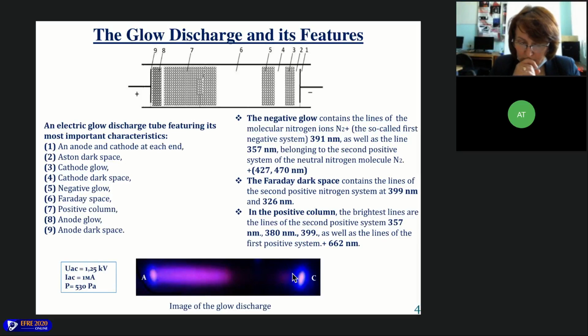There are 2 most important types of collision: excitation and ionization of gas atoms. The excitation collisions and subsequent de-excitation to lower levels by radiative decay are responsible for the characteristic glow in glow discharge. For example, the negative glow contains the lines at 391 nanometers, 357 nanometers, 427 and 470 nanometers. The Faraday dark space contains bright lines at 399 nanometers, 326 nanometers, and the positive column contains bright lines at 357, 380 nanometers, 399, and of course the brightest lines what we see here at 662 nanometers.